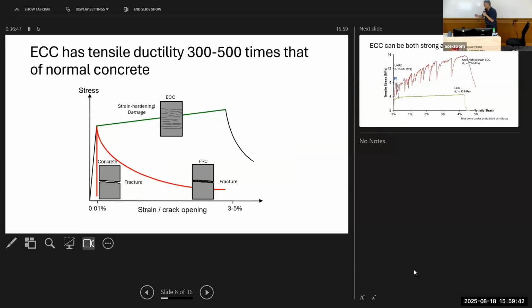Okay, so compared to familiar materials like concrete, if you pull a piece of concrete in tension, you have the elastic phase, and then suddenly a crack forms and the load drops to zero. So this is the common brittle fracture behavior of concrete material. If you put fiber in the concrete, you get a fiber reinforced concrete that, after the first crack forms, has tension softening when the fibers get pulled out or fractured, bridging across the crack. As the crack opens up, the fibers are pulled out or fractured. Okay, and